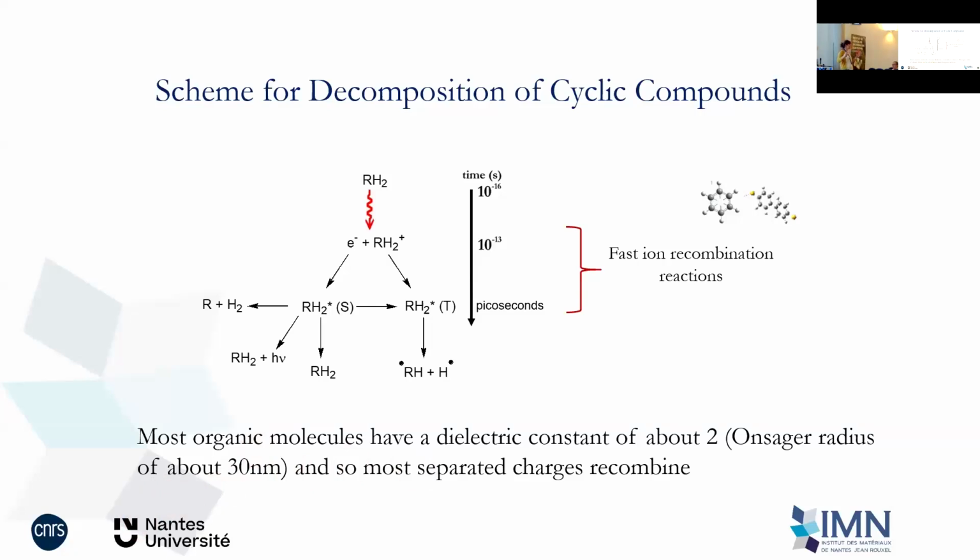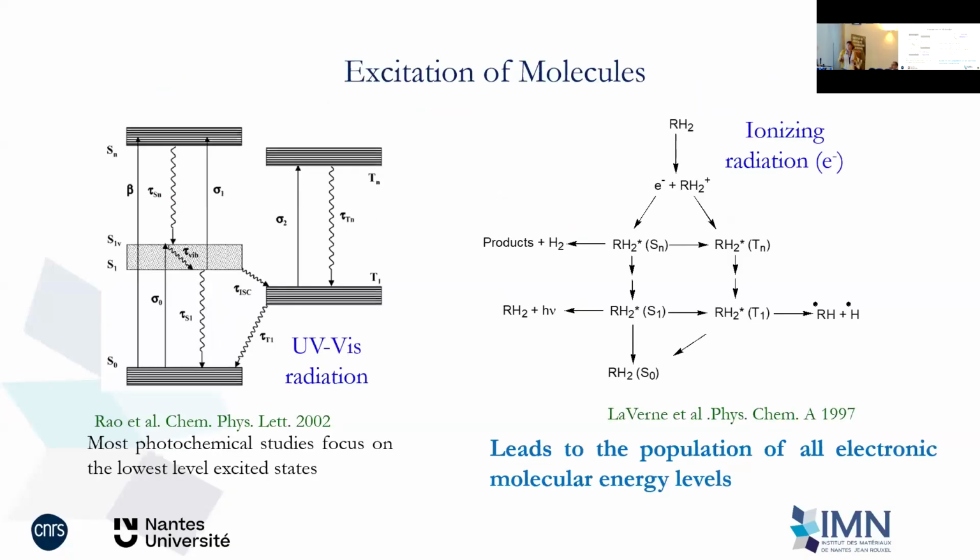So what is going to happen is that they're going to recombine, and you are going to end up with most of the damage, and in a similar ratio, so like the 95%, 90-something%, is going to come from excited electronic states and not from ionization. So these are two different things. And okay, so it's a bit different.